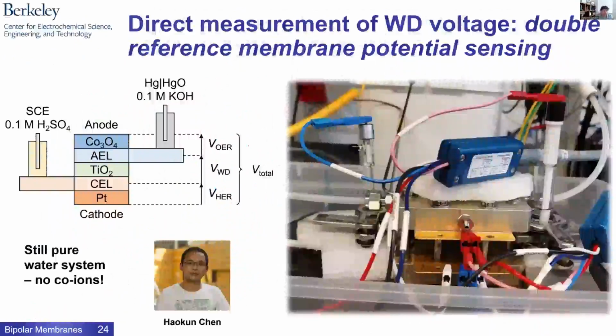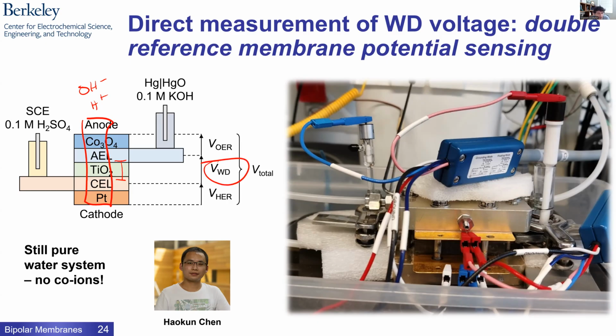So to look at these mechanisms and to try to get some useful data, we developed a more sophisticated sensing technique. The challenge: we built these MEA devices. The advantage is we have nothing except for OH minus and H plus as our free carriers. There are no other ions around. That's great. It's essentially a solid state device with liquid water hydrating all these layers. But it's harder to put things like reference electrodes in and to really accurately measure these interfacial drops associated with driving the water dissociation. So we developed techniques to do that, which I won't go into.